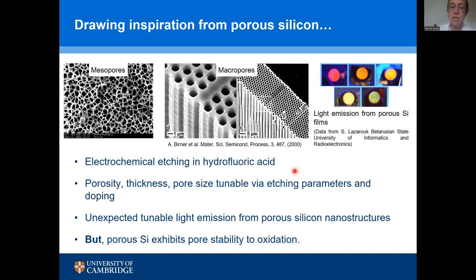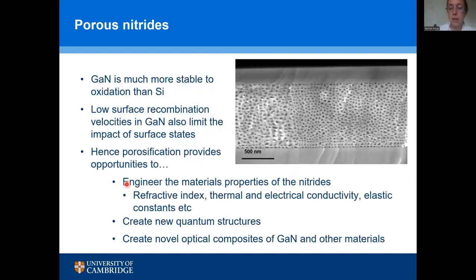So it's an interesting question to ask, what can we do with porosity in a material that's already direct band gap and that's like a bit of a classic now for light emitting devices? So now we come to gallium nitride then as our light emitting material. And if we think the problem with porous silicon for light emitters was its instability to oxidation, we're looking in gallium nitride at a material that's much more stable to oxidation.